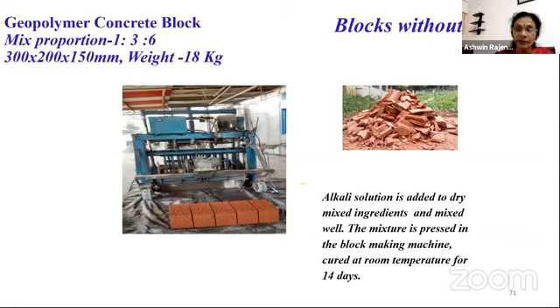Sometimes, certain types of waste materials are used as a source material for geopolymer. For example, fly ash is also used as a source material for geopolymer. Ambient curing won't give you significant results. In that case, we should go for accelerated curing, 60 degrees Celsius, 80 degrees Celsius for 24 hours, 12 hours, like that. But with this clay tile waste, ambient curing was possible. So definitely we can suggest it for normal manufacture of normal geopolymer blocks. So these are some of the researches.